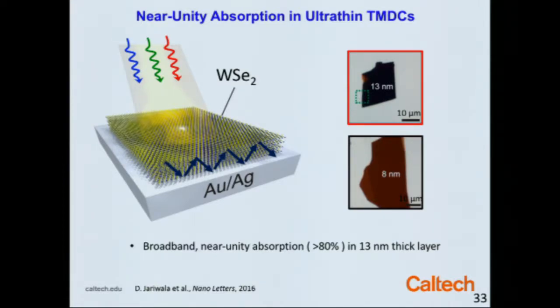You don't even have to do any spectroscopy to get the answer. All you have to do is use your eyeball spectroscopy. So here's an example: if we look at a 13 nanometer layer of tungsten diselenide sitting on a silver mirror, what's the first thing you notice about it? It's black. It should be transparent if it's a very thin material, right?